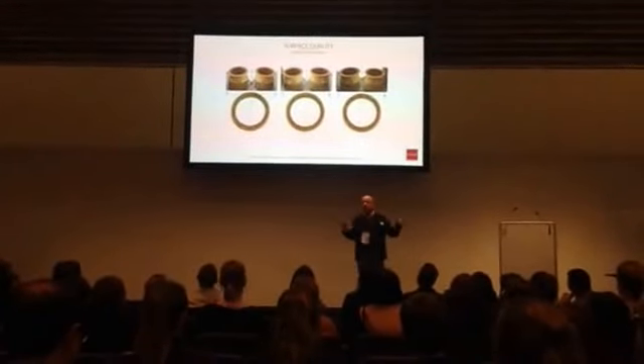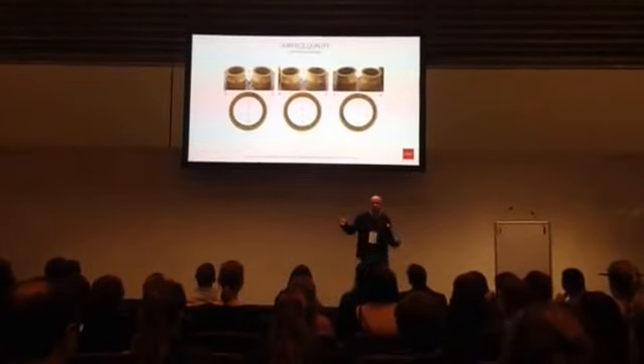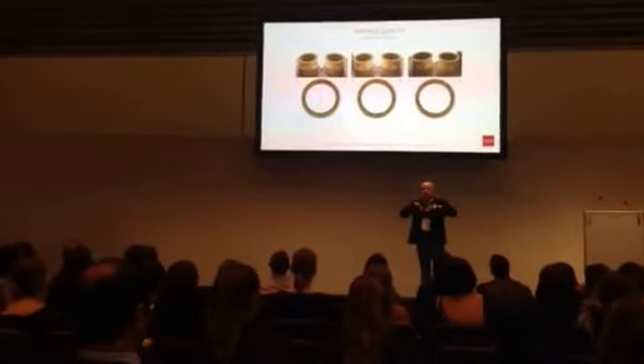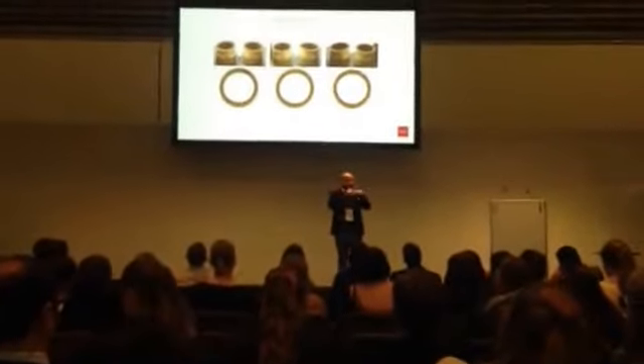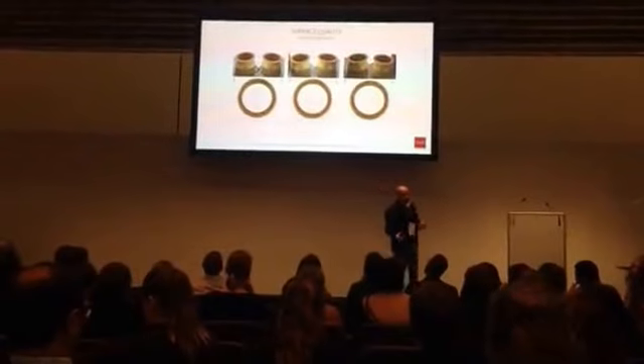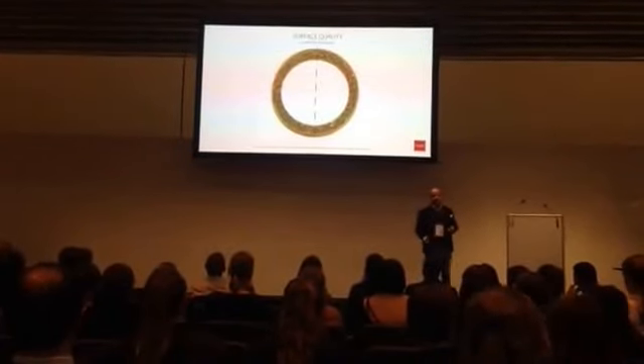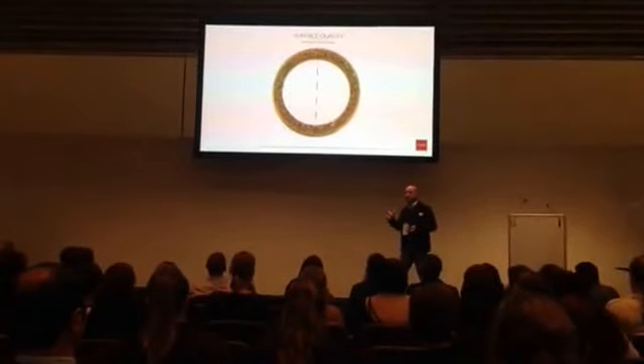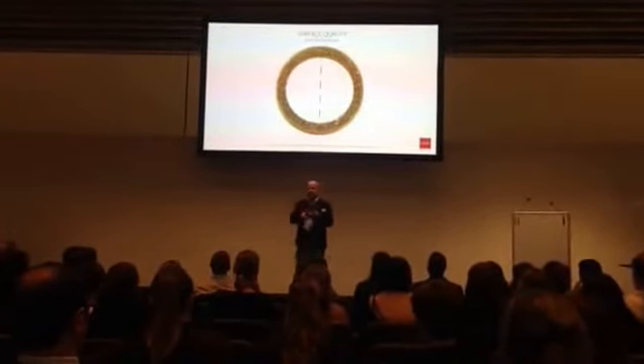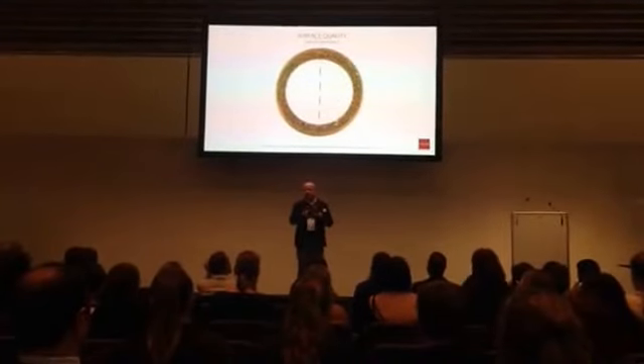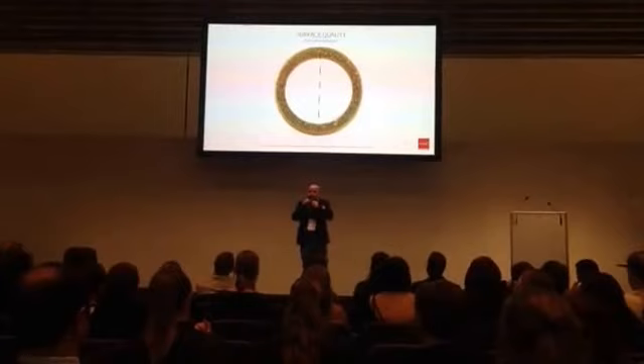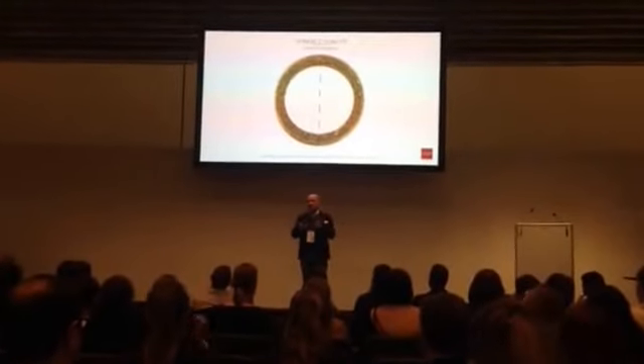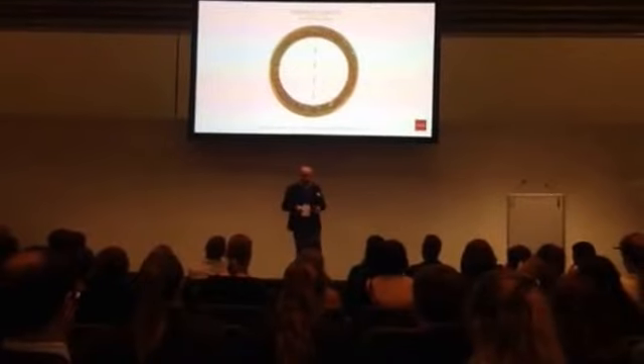This is something that we don't like in 3D printing. That is the support. So on the top image, you see different supports that are used for 3D printing. So there is block, volume support, so different strategies to hold the pieces on the building platform and to transfer the heat that happens during the melting. The kind of surface that you have when you cut the support is that one, which is comparable to the one when you cut the sprue, you cut the ingate, then you have to reshape those parts. Here we have many small ones in a bigger area. In case of casting, you have one big one in a smaller area.